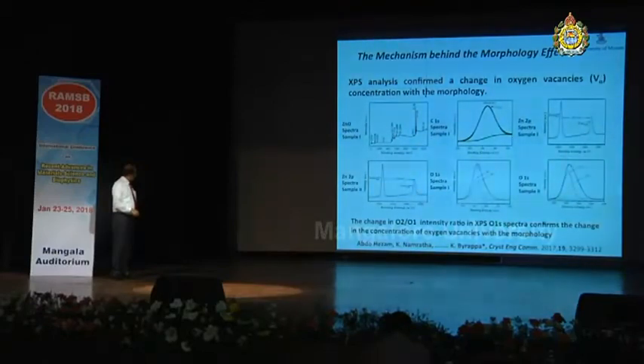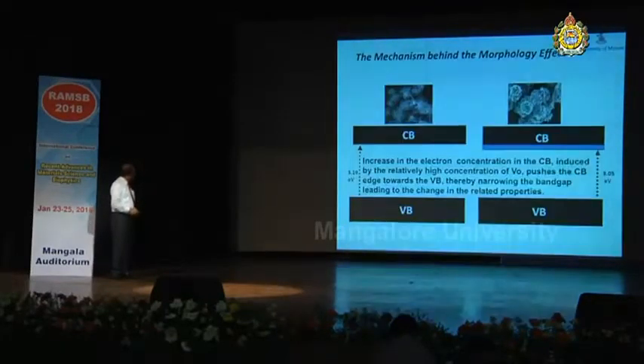O1S spectra, the oxygen vacancy spectra, confirms the change in the concentration of oxygen vacancies with the morphology, and this is the entire XPS spectra for the zinc oxide sample. This corresponds to, this is of course carbon, and sample 1, sample 2, zinc and oxygen, showing the different levels of vacancies.